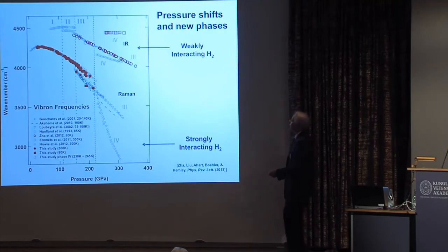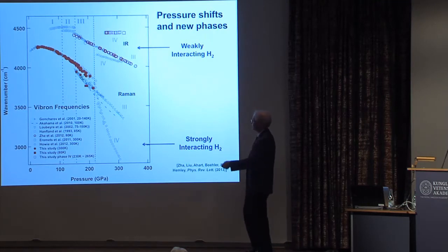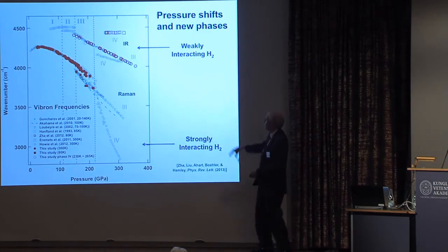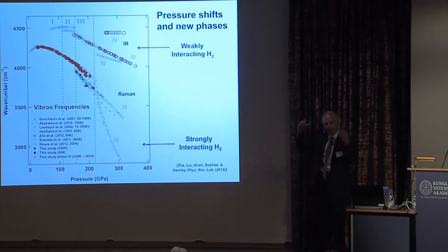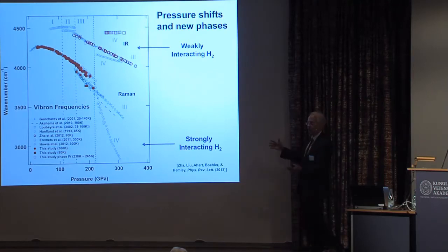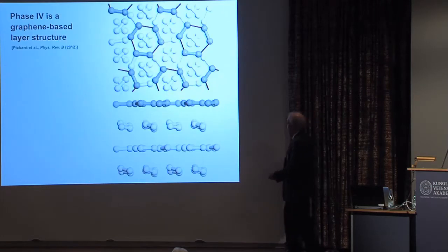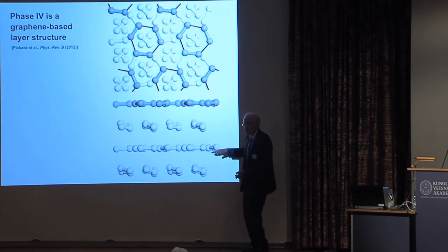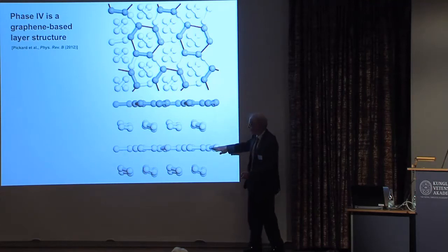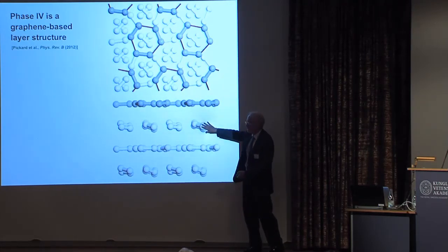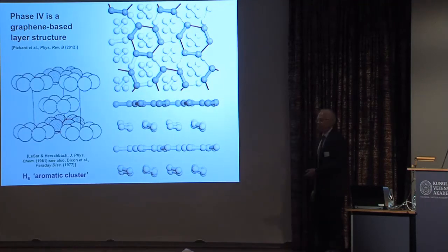Well, this is quite interesting now, because if you look at the vibrational frequencies, you see two different kinds of hydrogens, strongly interacting hydrogens, weakly interacting hydrogens in this structure. So again, an example of a very complex, now anisotropic structure, far from close-packed, a symmetry breaking of a high order, in fact, and this structure really, based on the analysis of the spectra and calculations, shows graphene sheets of hydrogen in a layered structure where you have the strongly interacting molecules in the graphene layer and weakly interacting molecules between them. This was a big surprise.